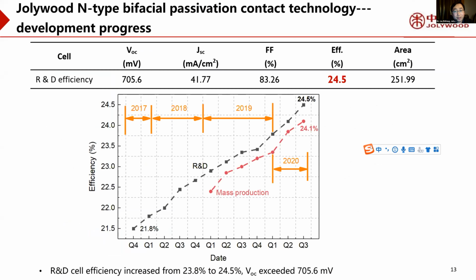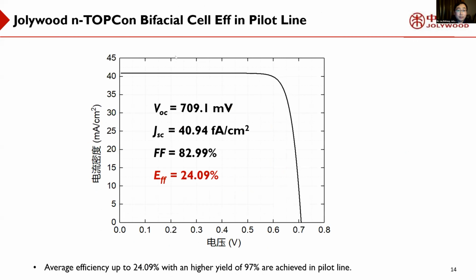This is the Jolywood N-type bifacial passivation contact technology development progress. We developed the TOPCon solar cell from 2017, and at that time the efficiency was just 21.8%. After 3 years of development, now we have achieved 24.5% efficiency in R&D. This is the pilot line in R&D. We can get the average efficiency of about 24.09%. This is the R&D pilot line.